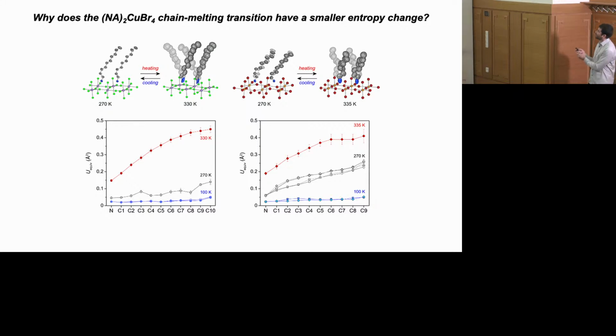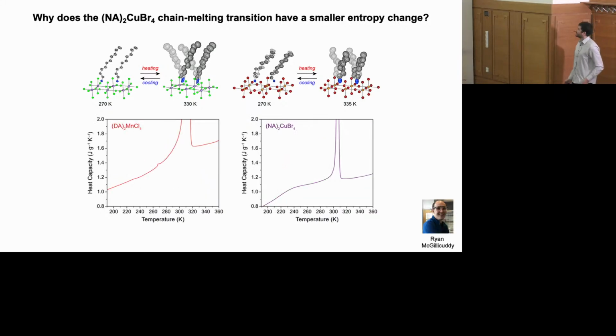So we still undergo a transition from a more ordered to a more disordered state. But the transition has a smaller entropy change, and this lower entropy state is actually closer in structure and dynamics to the higher temperature state. And so we think that there's a better match between these two phases, and so there's a lower activation energy barrier to nucleating one phase from the other, and that's what leads to this smaller hysteresis.